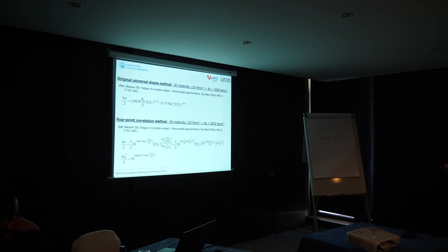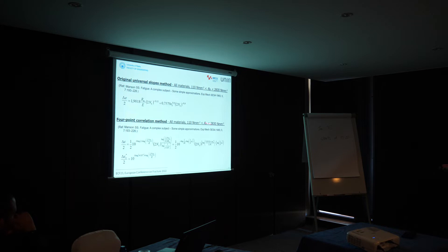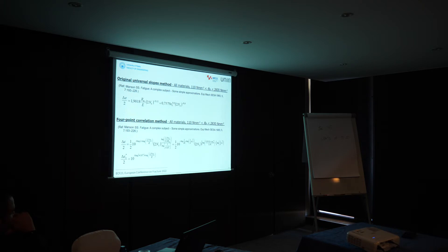We have some coefficient exponents approximated by constant values, and we can see this true fracture strain is used to estimate the fatigue ductility coefficient. A more complex expression is that proposed by Manson — the four-point correlation method — but already at first sight it is rather bulky and inconvenient. It also requires a number of parameters which are not readily available even from monotonic tests: true fracture stress and true fracture strain demand additional effort to determine.